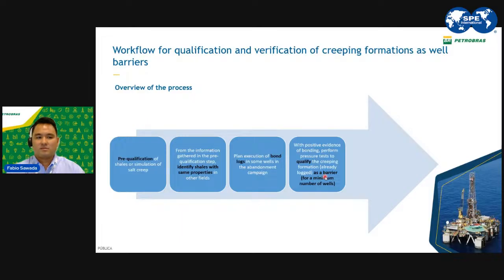I mean, when we talk about the pressure that we expect at the end of the life cycle of a well, we should perform the bond log and the pressure test in a certain number of wells that the operator should be defining in order to understand that that formation is qualified. So the qualifying process here would be understanding, correlating actually, the bond log response to the pressure test response, and making sure that the bond log response is enough for the formation to be defined as an element of a well barrier in a well. This would be mainly the philosophy of the qualifying process here.